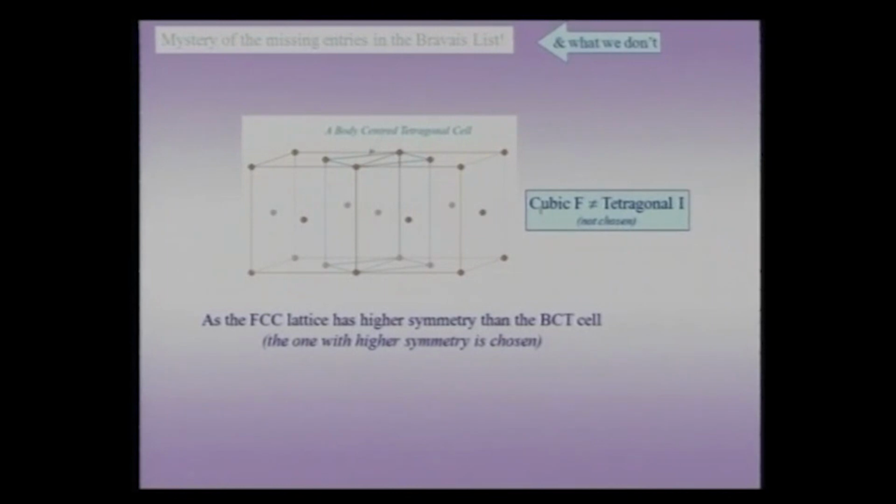but the lattice itself will always remain a face centered cubic lattice, because the description of that lattice is characterized by the 4/m 3-bar 2/m symmetry, which will not be destroyed by your mere choice of the unit cell. However, the conventional unit cell is the one which is chosen in orange.